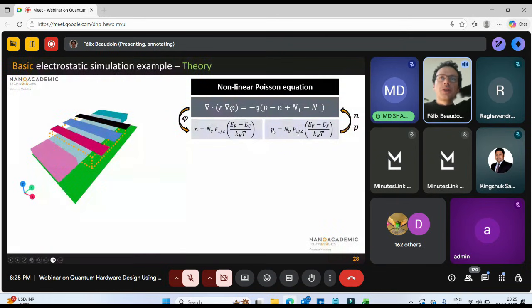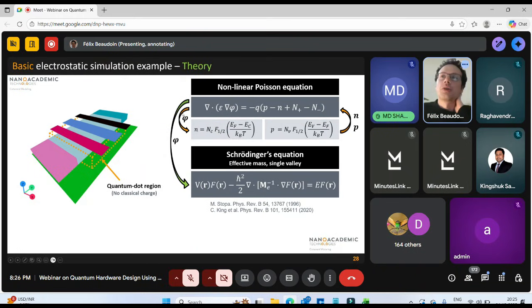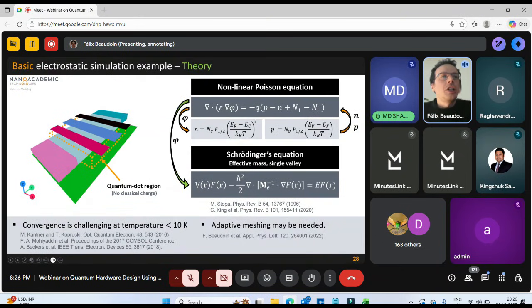Once we have converged this nonlinear Poisson equation and found the electrostatic potential throughout the structure, this defines the confinement potential. And then we can find the electronic structure of the quantum dot by solving an effective mass Schrodinger's equation for it. It's defined like this. So f of r here is the envelope function. This is the equivalent of a wave function at microscopic scales that are much longer than the atomic spacing. This is a notoriously difficult problem to solve because the nonlinearities associated with the electron and hole charges are much stronger at cryogenic temperatures. So adaptive meshing may be needed for robust convergence, and that's something we describe in this paper. So that being said, let's jump into the code and do the demo.